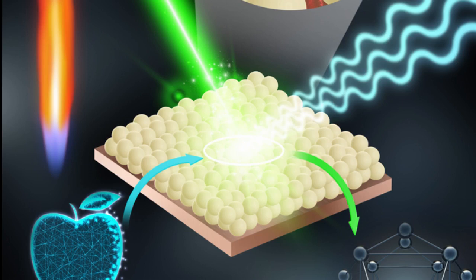To test their substance-detecting ability, they applied a thin layer of tracer dye on top of the sensors and used a spectrometer to uncover their molecular fingerprints. The sensors reliably and uniformly detected the molecular signals, and their performance remained intact when tested again after two and five months, which underscores their shelf-life potential and feasibility for large-scale production.